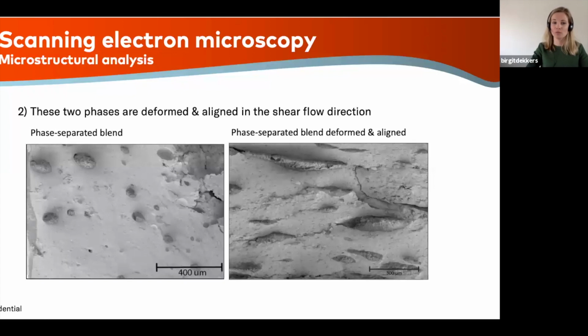Then if you bring this into the shear cell and you apply the right conditions, then you see that this second phase can be deformed and aligned in the shear flow direction, as you can see on the right side in the picture. So on the left side, you see a kind of blobs, a kind of spherical droplets inside of another matrix. And on the right side, you see that these blobs, these networks are deformed in the shear flow direction. In this case, these blobs can be even up to 300 micrometers, for example.